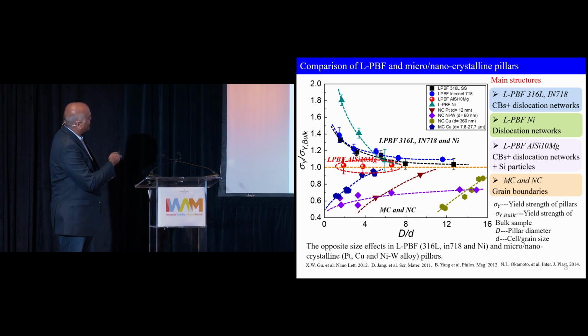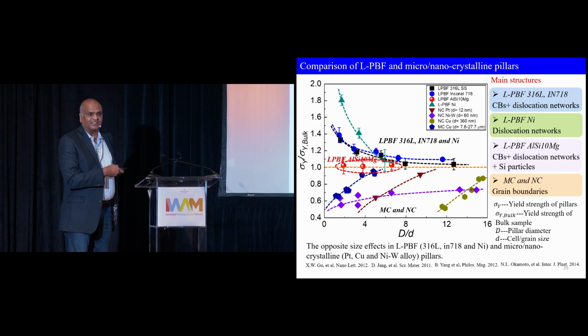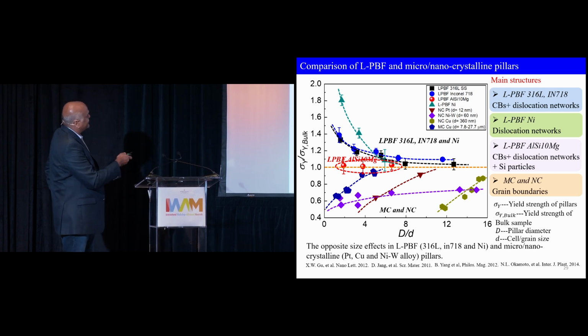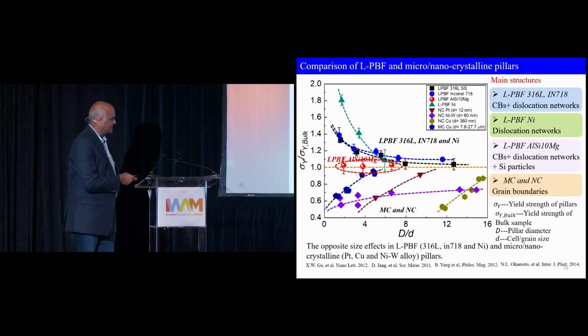So now, we normalize that with the bulk value, taking a very large specimen and measuring it. So in this axis, we normalize the pillar diameter. Capital D is the pillar diameter, with the cell or grain size. So if you have conventionally manufactured metals, microcrystalline or nanocrystalline metals, what you will see is that as the pillar diameter gets smaller and smaller, it's weaker. Smaller is weaker. But in 3D printed metals, it's smaller is stronger. You can see in all of the cases, it's mostly smaller is stronger, okay?